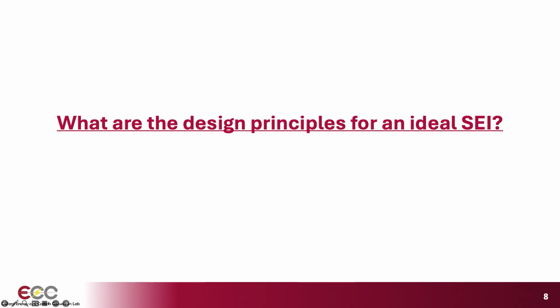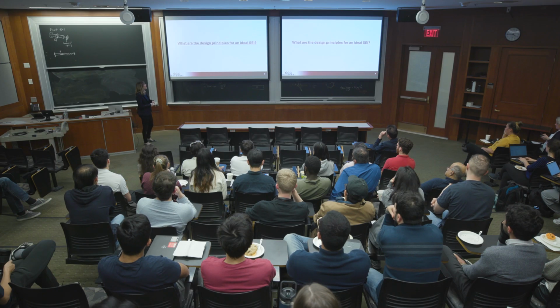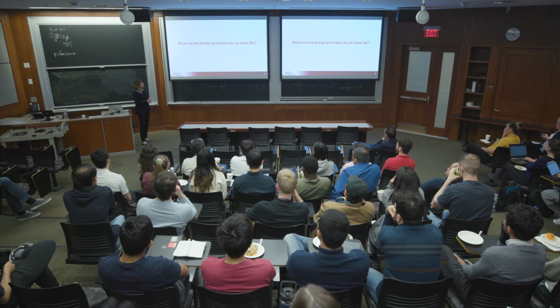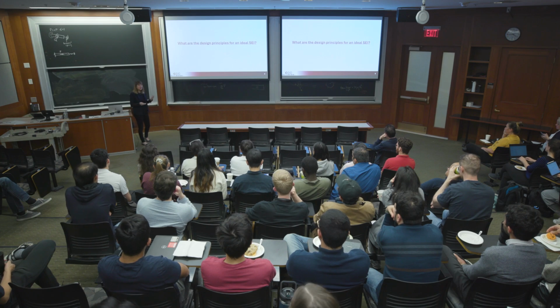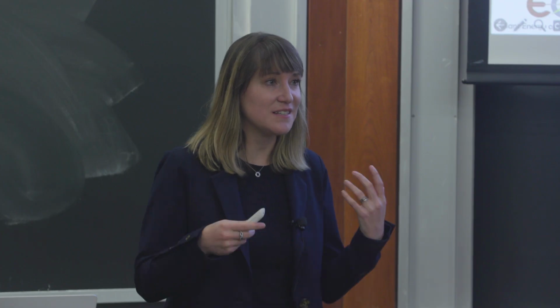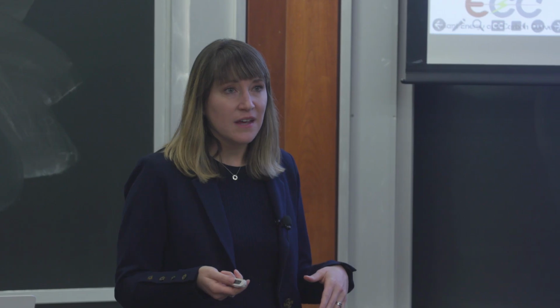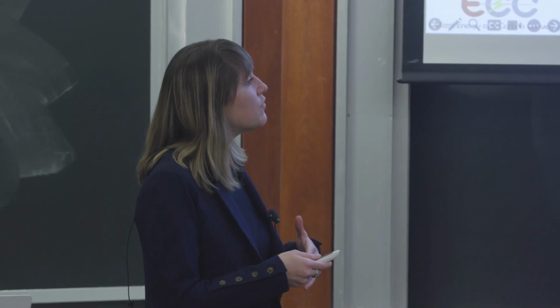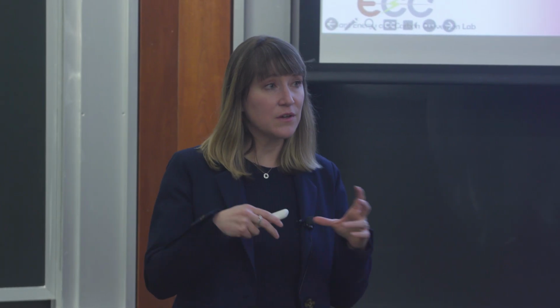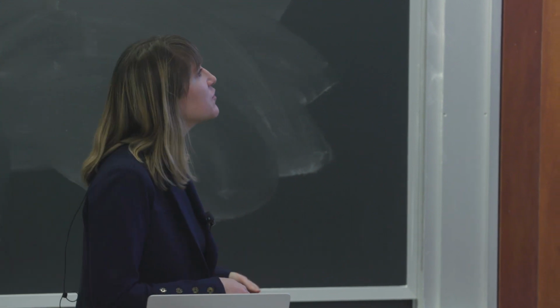So if we have to get the SEI exactly right, what are the design principles for designing a good SEI? It turns out that this is a question that has motivated the field for actually decades, and we still lack a really clear answer to this, and that's simply because the SEI is so challenging to characterize. It has nanoscale thickness, it's extremely reactive with air, it's unstable, very fragile. And our spectroscopy methods today, like IR, XPS, can be informative, but they're not sufficiently quantitative, and they're often only looking at a portion of the sample. They're not telling us about the entirety of the sample, which is what we need to understand to get back to thinking about capacity loss at an electrode level.